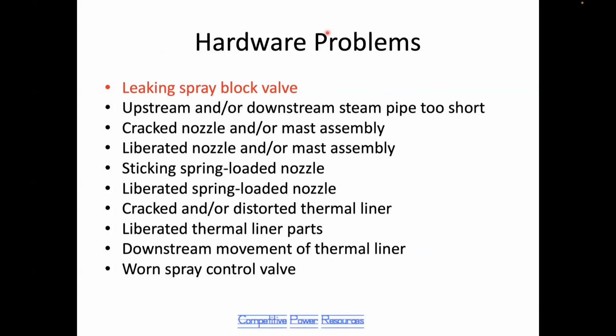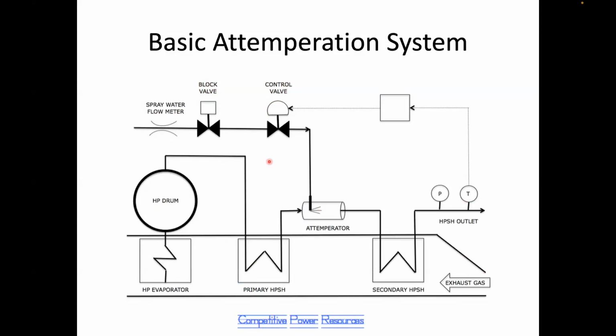So, hardware problems that drive thermal fatigue associated with the Attemperators. The most common, which happens in over 80% of the plants we survey, is leaking of spray water past the block valve. So this is a block valve. It is absolutely critical that this valve seal tightly and be shut off at the right times to avoid water entering the steam pipe when there's no steam flow. If it leaks when the unit is shut down, the water leaks into the steam pipe, and it's very likely that it will crack the steam pipe.